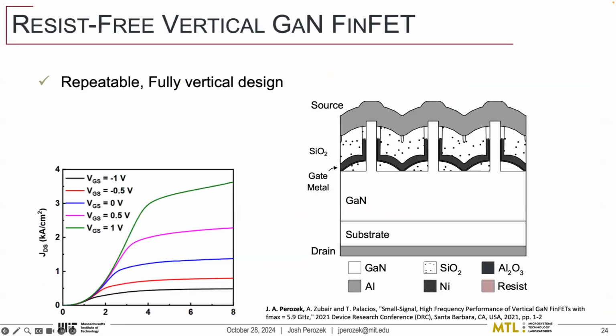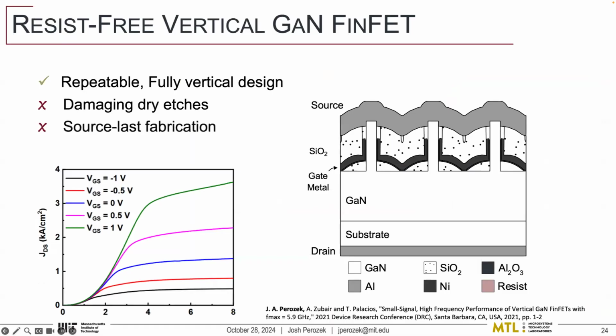So while we're able to get a repeatable, fully vertical design, what we couldn't do was avoid these damaging dry etches. It was a source last fabrication, so putting the source contact on, you had to go through all of these damaging steps. And it really still required that you be very careful with etching back these steps. I would spend literally days doing a single etch, going back and forth between an electron microscope and the dry etching tool, which was really difficult when those were in different buildings. So that took some time.